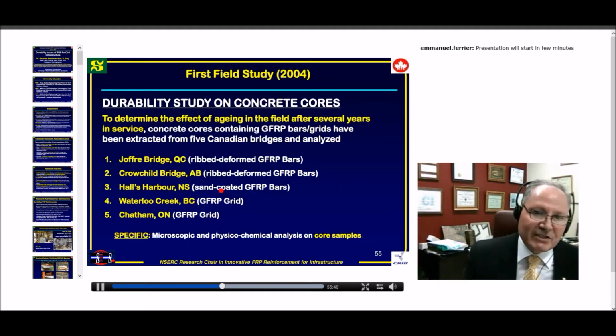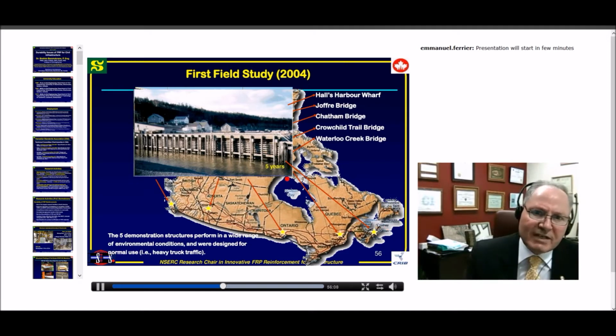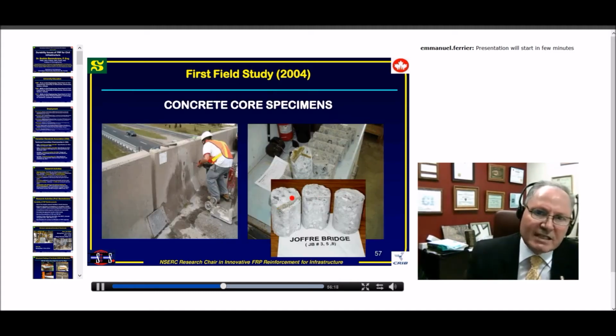all these 5 bridges: Joffre Bridge here in Sherbrooke, Crowchild Bridge in Alberta, close to Calgary, Halls Harbour in Nova Scotia, Waterloo Creek in British Columbia near Victoria, and Chatham in Ontario. And we did microscopic and physico-chemical analysis, looking under the microscope. So we took cores from all these structures and from 5 demonstration projects. You can see here the cores and the bars. We took them from the barrier walls, from the sidewalk, and from the slabs, and so on.